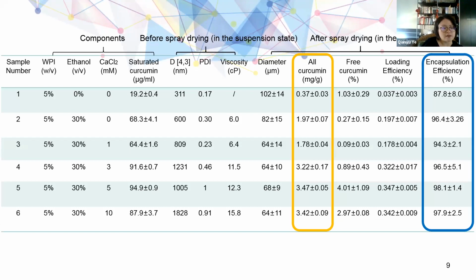This slide summarizes the parameters and compositions of samples 1 to 6 as prepared. I would like to emphasize 2 points. Firstly, in the spray-dried state, the curcumin contents of samples 2 to 6 upon denaturation, which is highlighted in the yellow circle, are up to 3.47 milligrams per gram of particles, mostly 1 order of magnitude higher than that of sample 1 without denaturation. Secondly, all samples displayed good encapsulation efficiencies, higher than 87%.